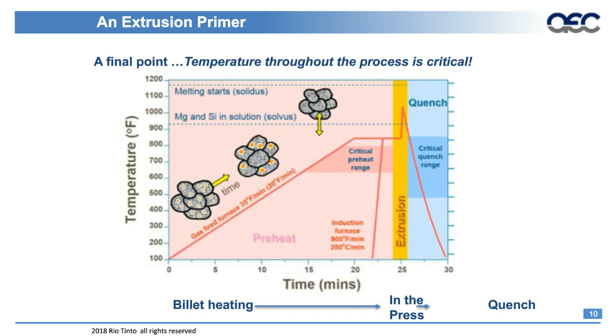So again, I mentioned the heating and the cooling process. What we're doing in that, and you can see from this diagram, starting on the left, is basically down around room temperature. Once we start to move that billet into the billet heater, we're beginning to heat that up, and that process takes a very varying amount of time depending on the diameter of the billet that's being pushed, or the length of the billet, or the alloy, but there always is a prescribed recipe for that particular shape as to what temperatures you're trying to achieve along the way. So you can see, starting from the left and moving to the right, that you're taking that billet, you're beginning to heat it, and you're getting it to a preheated or pre-extrusion temperature of around 800 degrees. Like I said, it will depend on what the alloy and then also the shape is, but it'll be somewhere around in that area.